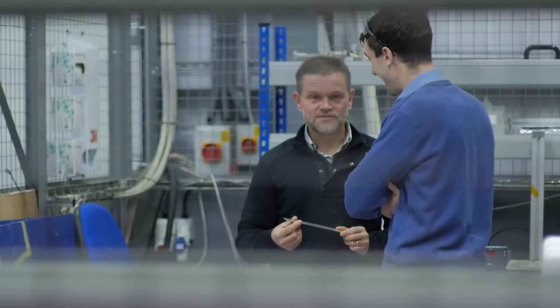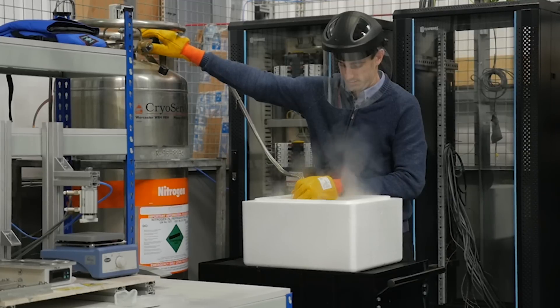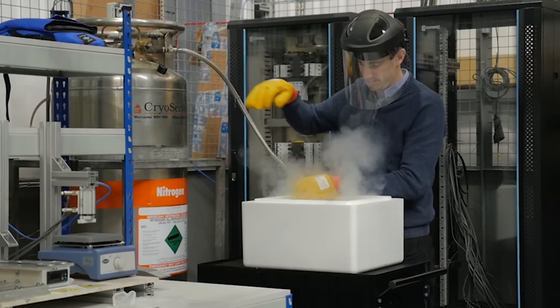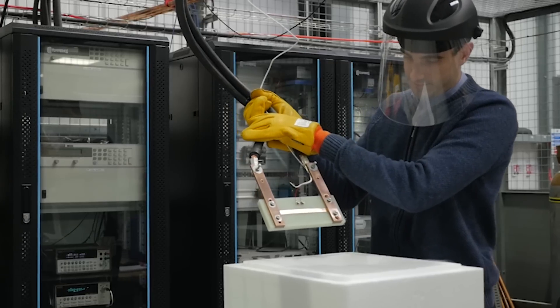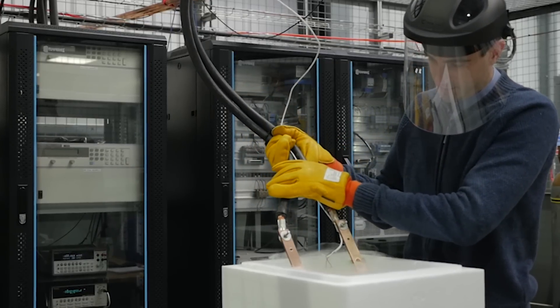There are lots of things you have to think about. Quench protection is a big issue for a high temperature superconducting magnet. Quench is just a generic term for if the superconductor stops being a superconductor, it becomes a resistor. And instead of current passing without dissipating any energy or producing any heat, suddenly energy is dissipated and the superconductor starts to warm up so you get a thermal runaway situation.